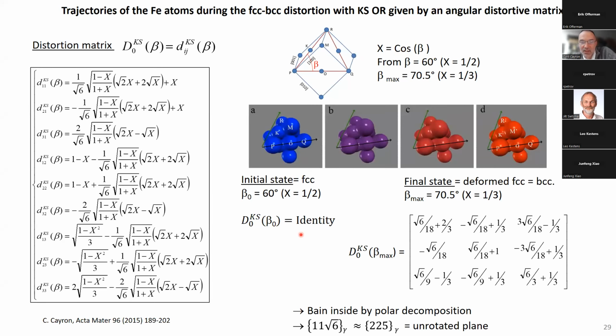If I can do it continuously, I can calculate the distortion matrix from the beginning. At the very beginning, it's identity, I changed nothing. And at the end, it takes this form here. But I can calculate all these intermediate states. It depends on x, as x is the cosine of this distortion angle. So I can make a movie. It's not DFT, it's not molecular dynamics, it's a simple hard sphere model to make a movie of what could be the phase transformation.